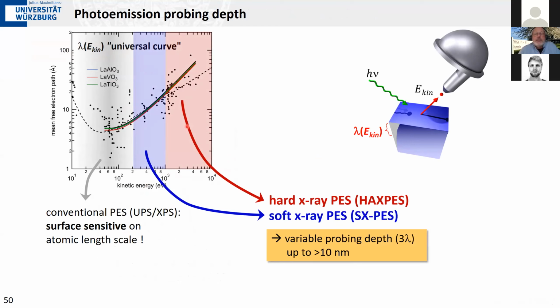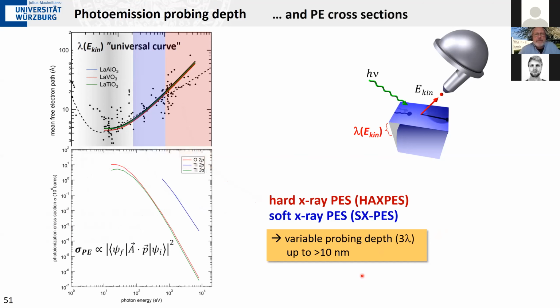And if we do this and go to even kilovolts, this is called hard X-ray photoemission, you can get probing depths of the order of up to 100 angstroms and beyond, which is in certain ways still maybe surface sensitive, but no longer on the atomic scale. And that's important here. The price you pay is that at the same time, the cross sections, this is the matrix element again, between initial and final states, is strongly going down by orders of magnitude as you go to high photon energies. And of course that costs you intensity.